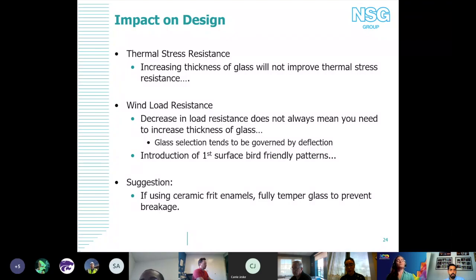Where this impacts design and leads into some of the discussions that you had on your podcast previously is a lot of the breaks are happening due to thermal stress. And so what things have an impact on thermal stress resistance? Well, one of the recommendations that someone on the team said was, okay, well then I'll just design with a thicker lite. If you're getting this load reduction, you could design with a thicker piece of glass, give it a little more strength. But whenever you're designing to resist thermal stress, increasing the thickness of the glass doesn't improve that stress resistance.